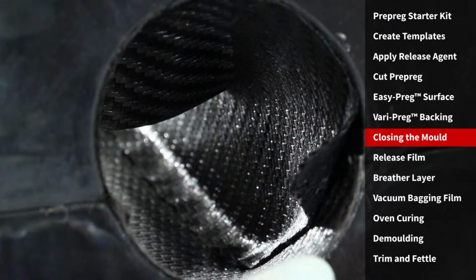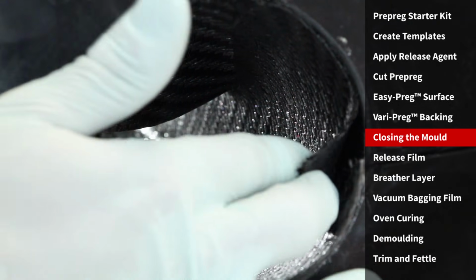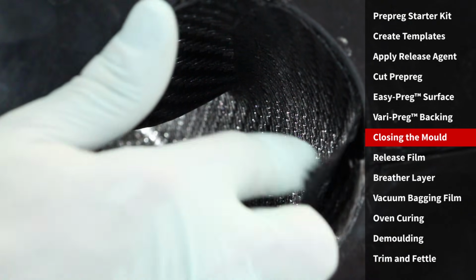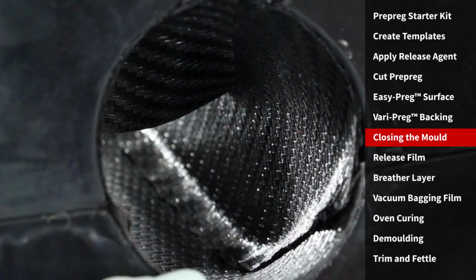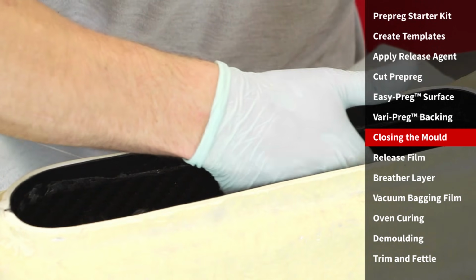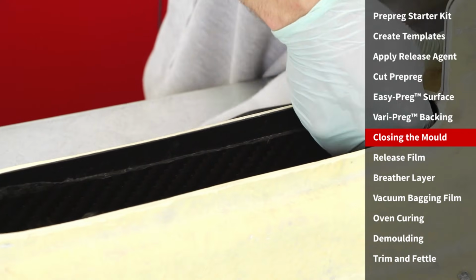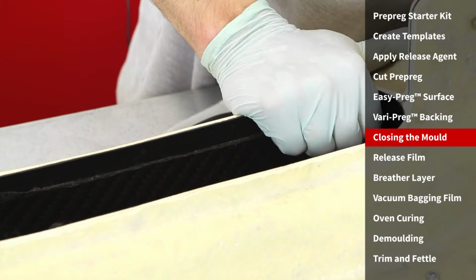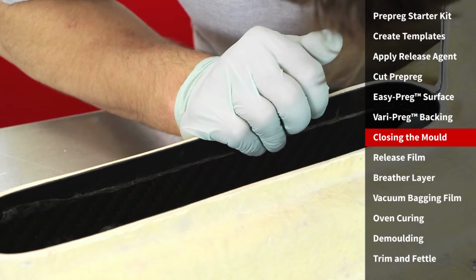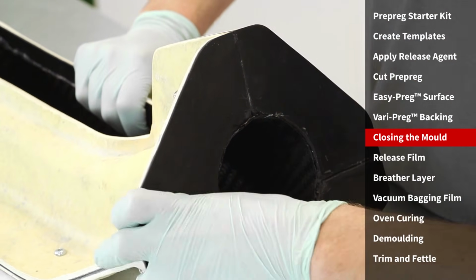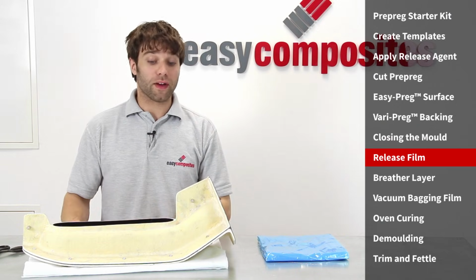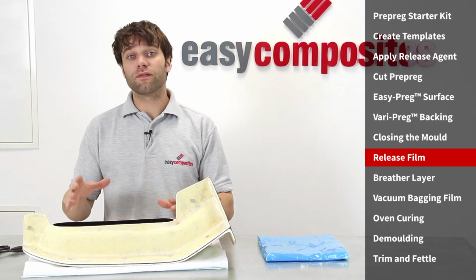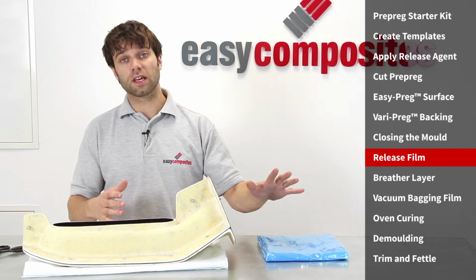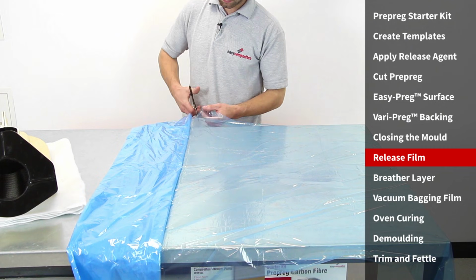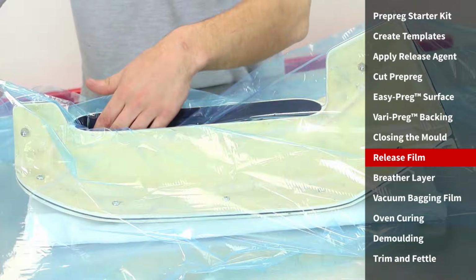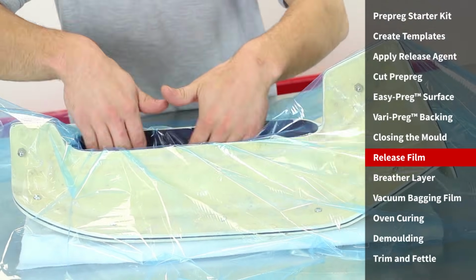Now we've got these two mould parts bolted together, you can see the extension that we left on the lower part of the section will overlap over the upper part, making a very strong bond between the two. With the layup complete, we're now going to move on to the vacuum bagging. It uses a completely conventional vacuum bagging stack, so we're using the materials that come in the kit, starting with the unperforated release film, followed by a breather layer, and then we're putting that into an envelope vacuum bag.